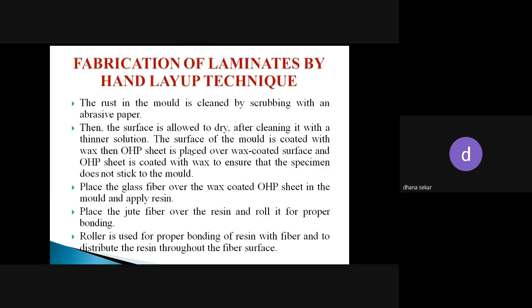After the epoxy resin, we placed the jute fiber over the epoxy, and again we rolled it for better bonding and equal distribution of the epoxy resin. Like this, we used 11 layers, that is 6 of glass and 5 of jute fibers. This is the procedure we used to fabricate the glass and jute fiber composite laminate. Then, second, we fabricated the glass and jute with eggshell additive composite laminate. In that, we just added the eggshell additive in between the jute and glass fibers. That is the difference.